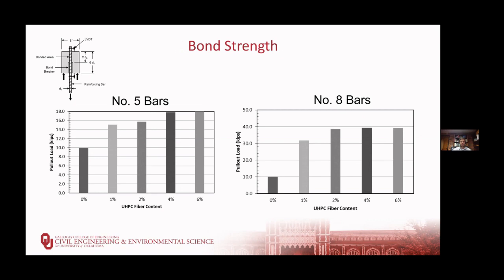Shown here, we have our different fiber contents, and we can see that for number 5 bars, we have a significant increase in bond strength going from 0% to 1% steel fibers. We don't see a lot of change from 1% to 2% steel fibers. And then once we get past 2%, we kind of flat line on our bond strength. It's very similar for number 8 bars, but we do see an increase between 1% and 2% steel fibers. But beyond that, again, we kind of have a flat line on our bond strength.